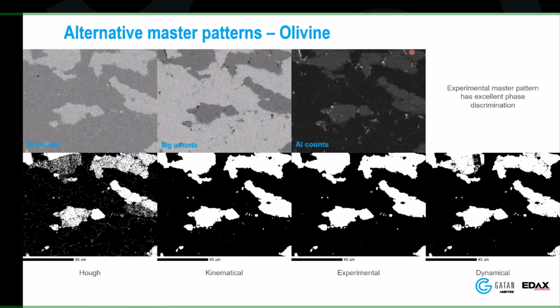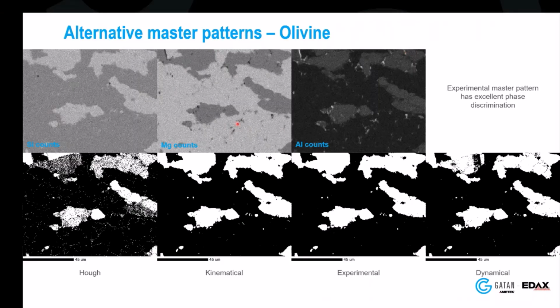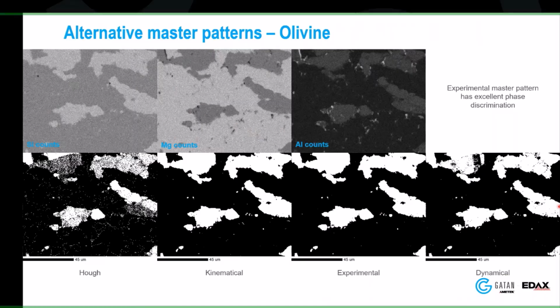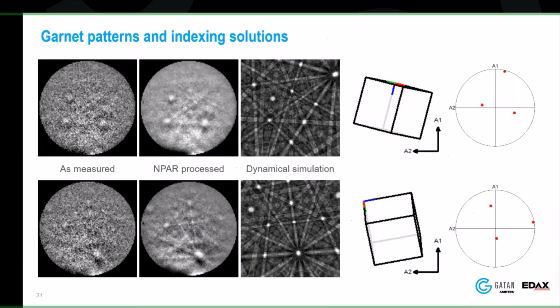And again, this is showing you a more multi-phase sample using olivine, here using the magnesium as a proxy. You can see that it does a really good job of phase discrimination as well. Here are the phases down here, we can see these big bright spots. So the experimental master patterns do a good job of pulling it apart without having to deal with things like chi-scan.